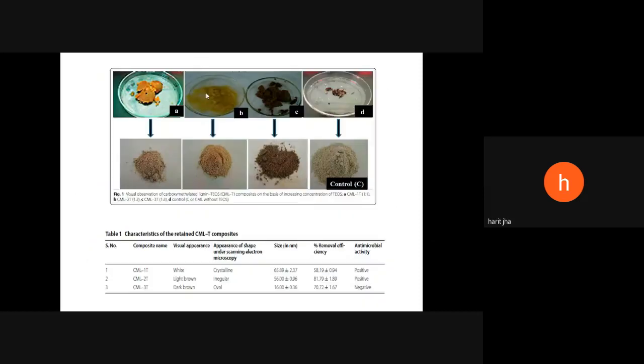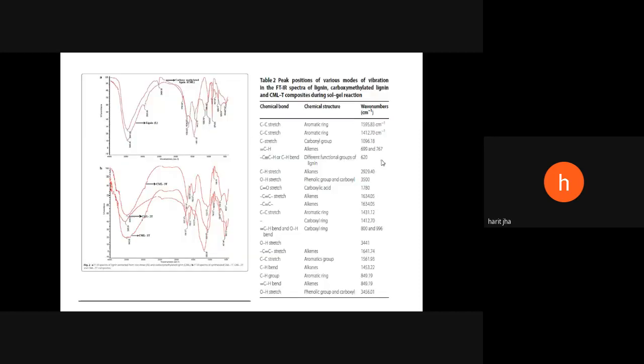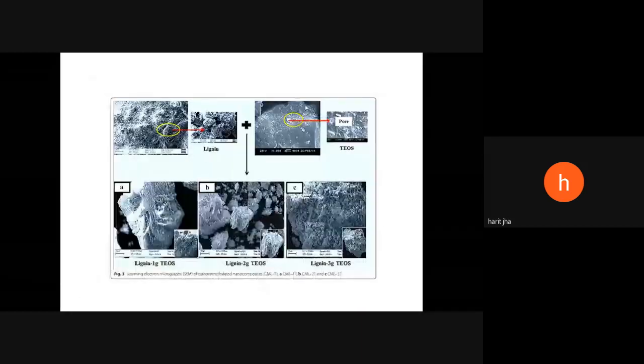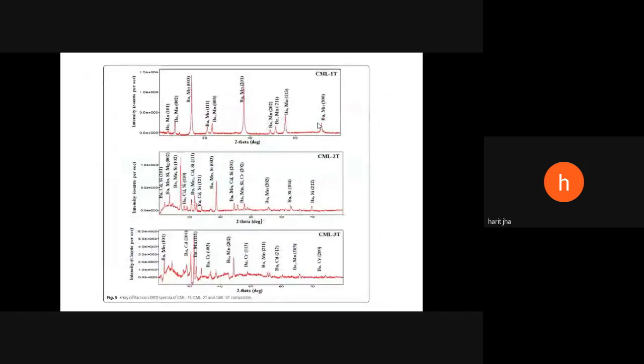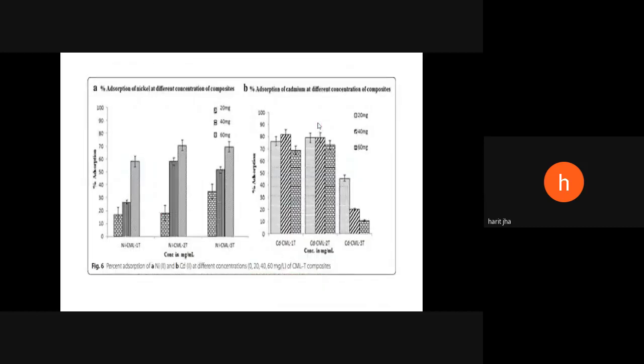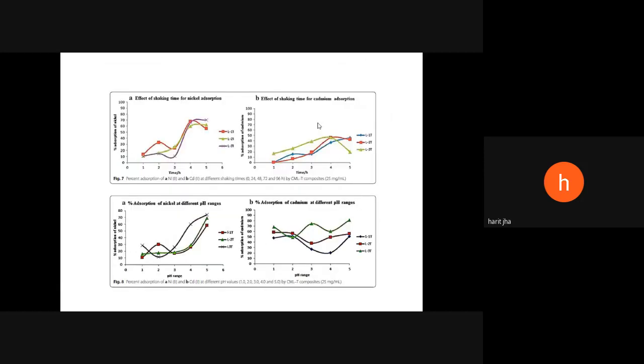These are the carboxymethylated lignin which we have used with the increasing concentration of TEOS. Okay, these are the visual appearance and visual appearance under the SEM and the antimicrobial activity. As you can see that at a particular concentration they have high antimicrobial activity. These are the FTIR, then SEM showing the surface properties, then XRD and adsorption of nickel and cadmium. The effect of different conditions like shaking time on adsorption of nickel and cadmium.